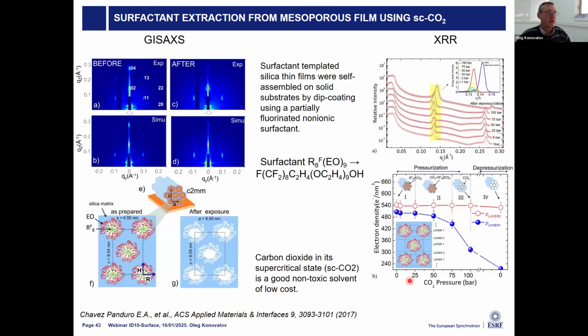pressure. And this is also the same type of measurements, but with mesoporous materials, how they wash out the surfactant from the pores. And then we can follow this process depending on the pressure of the CO2.